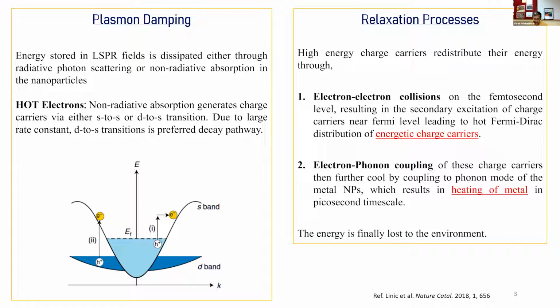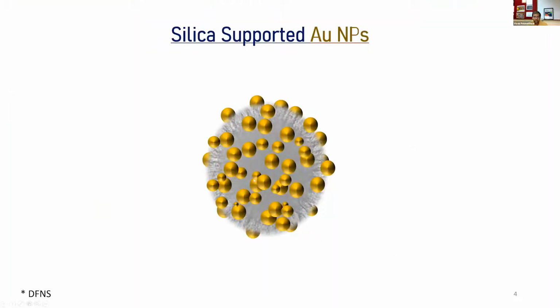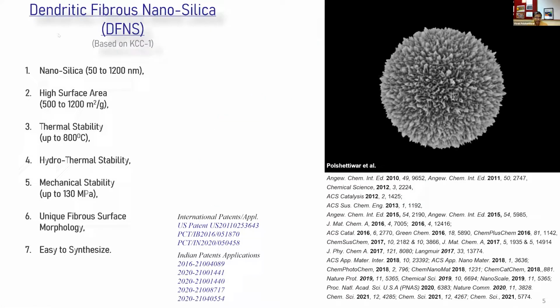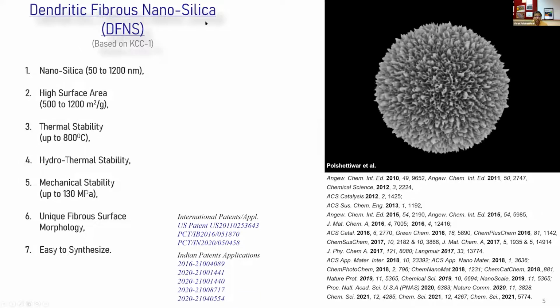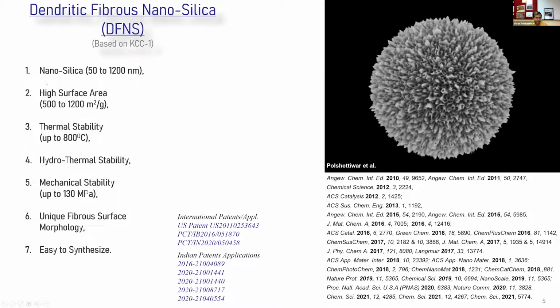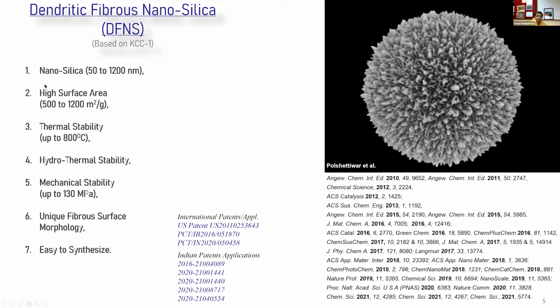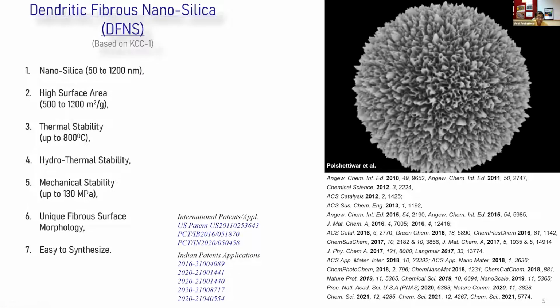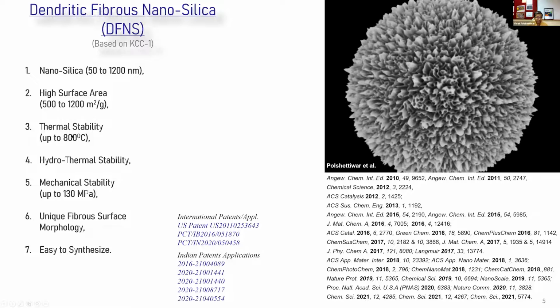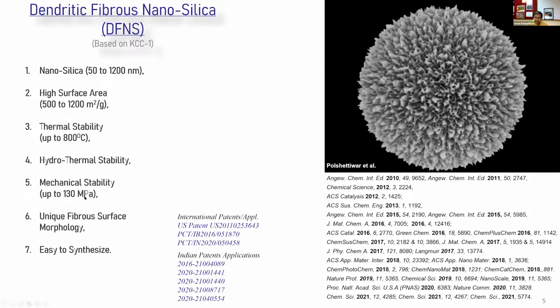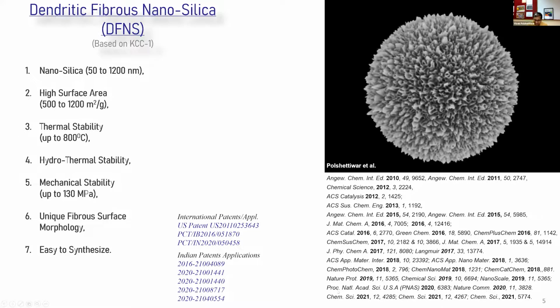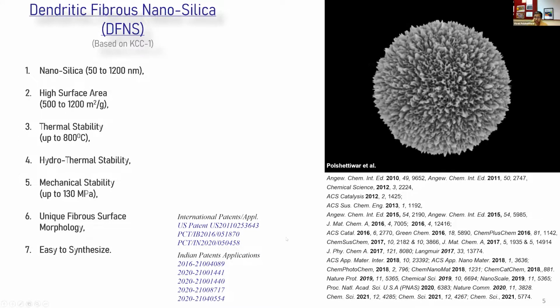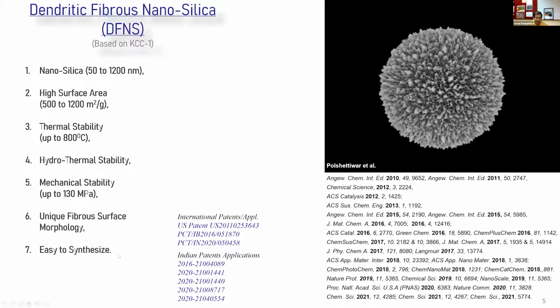So how do I now synthesize a material which will harvest the light as well as act as a heterogeneous catalyst? That means it should have a high surface area and better porosity. So we decided to load the gold nanoparticles onto a high surface area silica surface. This is one of the materials that we have developed in our lab: dendritic fibrous nanosilica, DFNS, where one can tune the particle size from say 50 nanometers to 1200 nanometers, with excellent surface area, thermal stability and mechanical stability. That means I can use it for high temperature, high pressure processes, and it's easy to synthesize. Recently, we wrote this Nature Protocols paper where we gave a stepwise synthesis, including videos, and now one can synthesize this in any lab in large quantity.